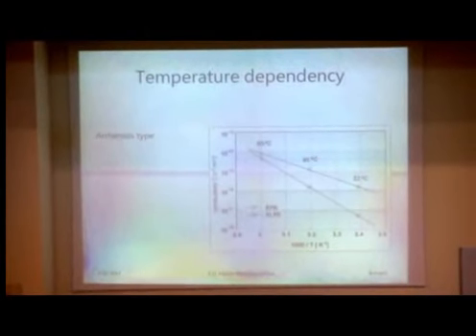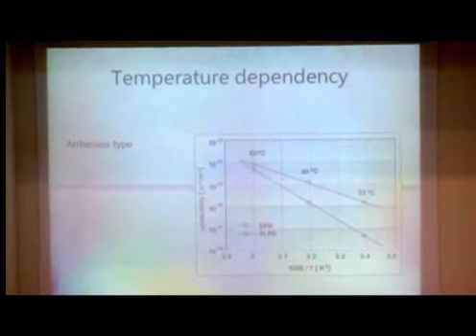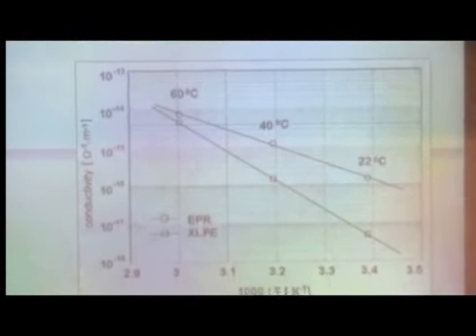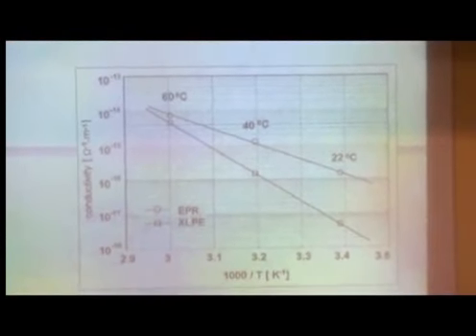For this temperature dependency, you have to do measurements. You can measure, for instance, the conduction current as a function of applied field, and you plot that in an Arrhenius graph. And usually then you get these nice lines. Here you see the Arrhenius plot for two different materials, EPR, the one here, and XLPE. These are two typical materials for HVDC cable systems.